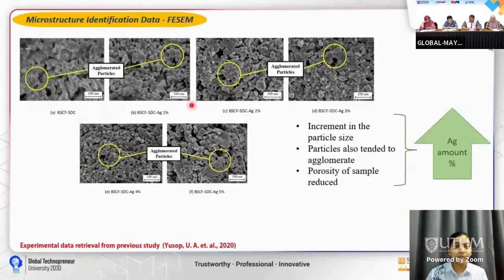So the next will be the microstructure identification data, the second data that we're going to use, which was gathered through the FESEM. And from these pictures, we can see the agglomerated particles. So the author stated that when the Ag was added in an increasing amount, there is an increment in the particle size, and the particles also tended to agglomerate with each other. And she also stated that the porosity of the sample reduced when the Ag amount was increased.